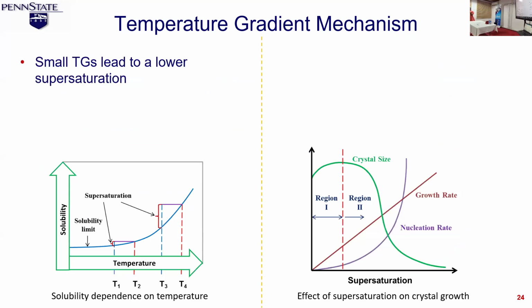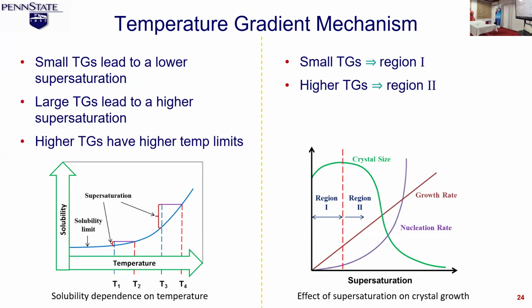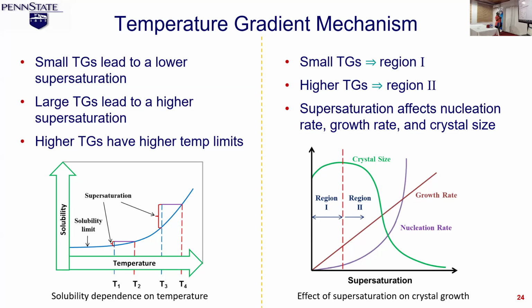In terms of the crystal size, I'll focus more on the image on the right-hand side, where we have the nucleation occurring, typically what we call supersaturation. So when the solute is really saturated in the solvent, we call it supersaturation. Now, if you have low temperature gradients, your supersaturation tends to be low. As you increase the temperature gradients, the supersaturation tends to be high. So in region 1, you would get a good crystal size even with the low temperature gradient. As the temperature gradient increases, your crystal size will still be good, but there's a point where it diminishes, right? The crystal size starts to decrease.